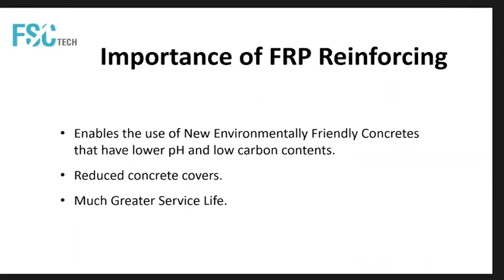FRP reinforcing is actually getting more and more important, mostly because the new environmental impact rules are pushing cement producers to make concrete that is more friendly from an environmental standpoint. And all those concretes basically have lower pH. The game to obtain a better and more environmentally friendly concrete is basically to convert some of our calcium hydroxide with CO2 into calcium carbonate, which obviously is a little stronger and sets faster, but lowers the pH, which means that it's no longer providing passivation to the steel.